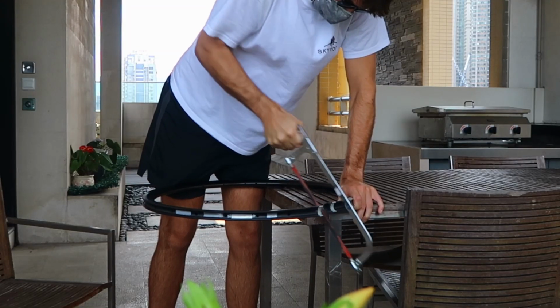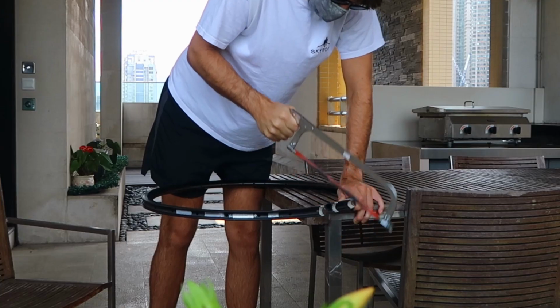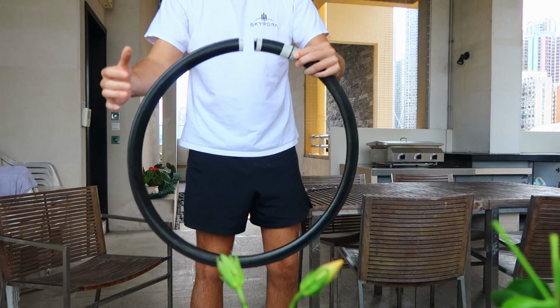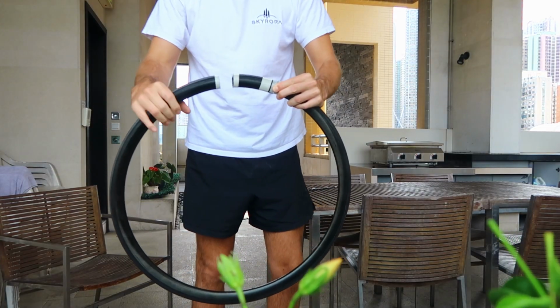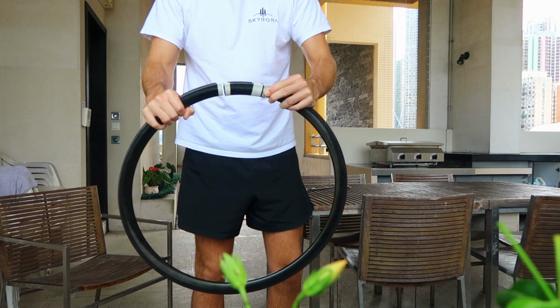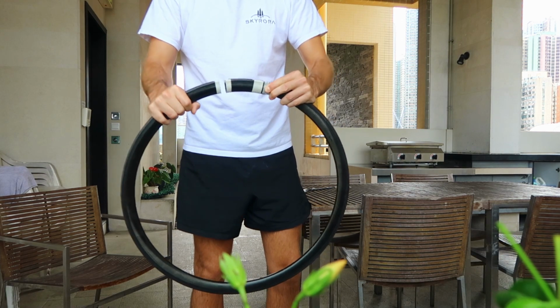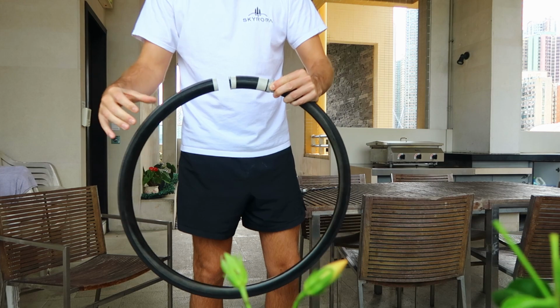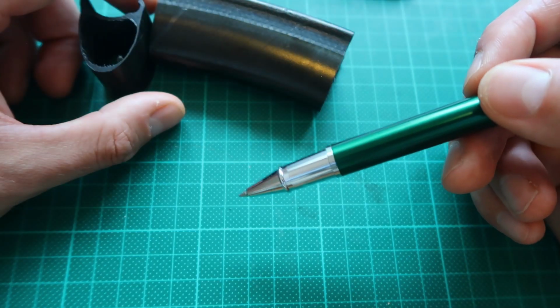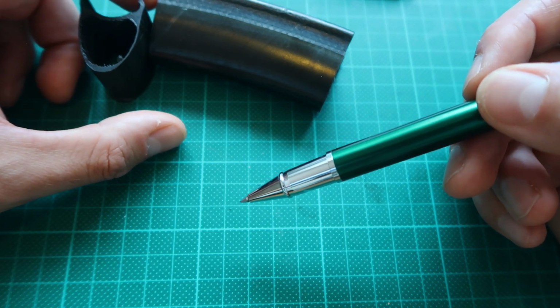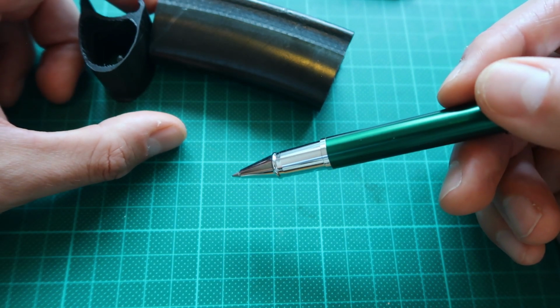Well, there was a lot of residual stress in the hoop of the rim after curing, probably. So after it's cured, there's a lot of captured stress inside of that hard rim, probably due to mold shrinkage. And as soon as I cut into it, bang, it snapped apart quite a lot. You can see that here.